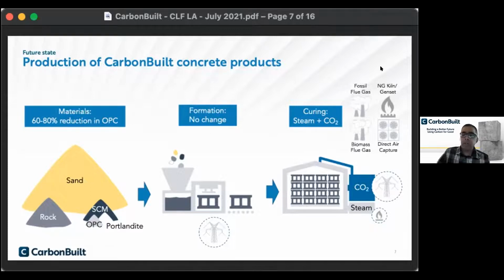So it's important to say that instead of one or two curing chemistries, as you would have if you were using Portland cement, maybe with fly ash, when you add our technology in, you have three different chemistries happening in the curing process. You still have cement hydration. This is happening over hours and days. So you have early strength starting immediately during the curing process, but there's strength that evolves over a month, let's say.